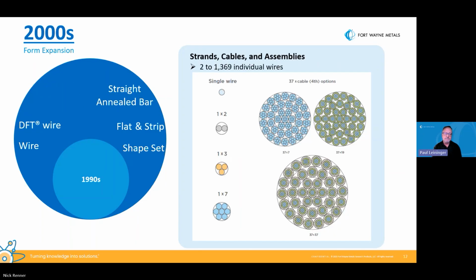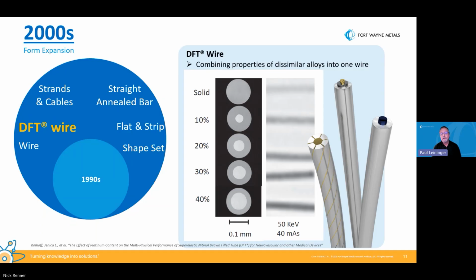As we take a look at some of the images on the screen for the DFT wire, the image on the far right is a good illustration of the different forms that the DFT wire can take. As we look at the cross sections in the middle of the screen, each of those cross sections compare the advancing and higher fill ratios compared to a solid core. The middle images show a DFT product formed into a coil construction. You can see how there is improved visibility under fluoroscopy, comparing the core to the 10% and all the way up the ladder to the highest fill percentage available in our standard range at 40%. So those are really useful for products where either sizing or placement and visualization under fluoroscopy is important.